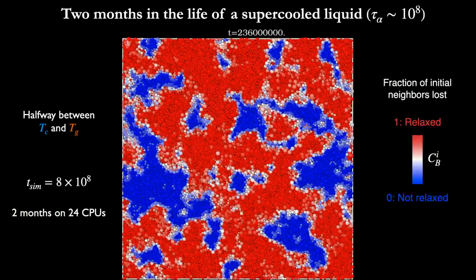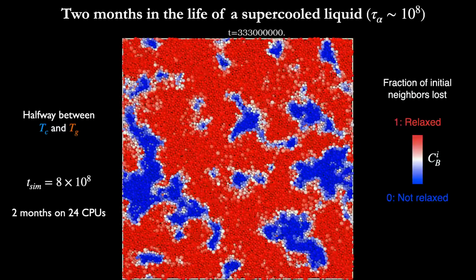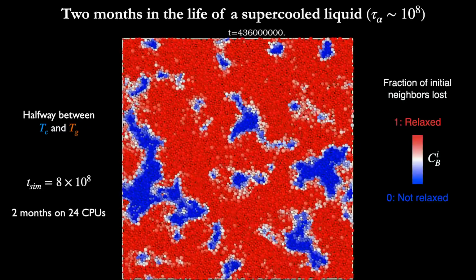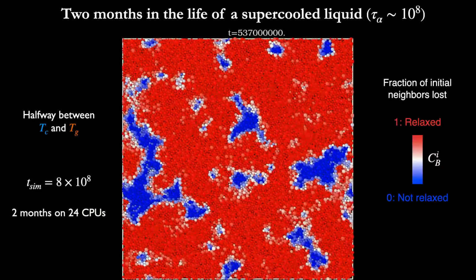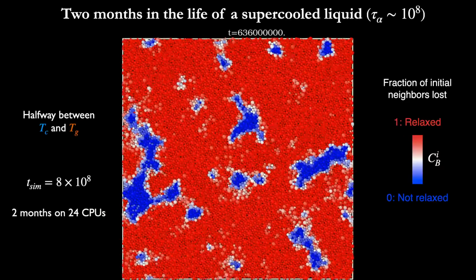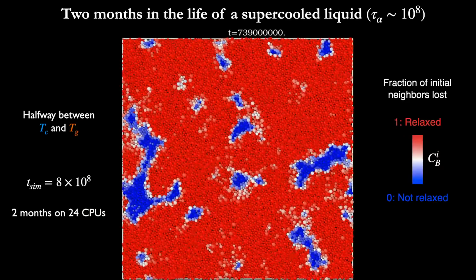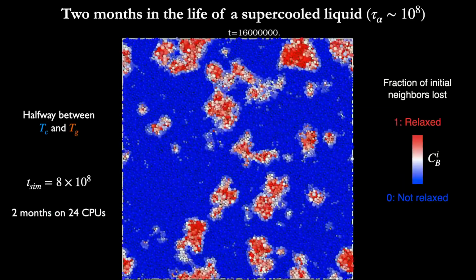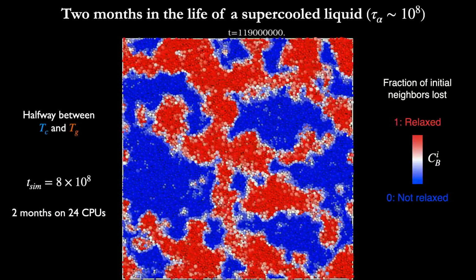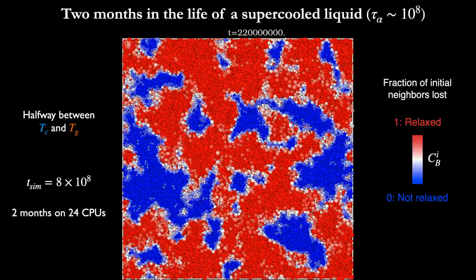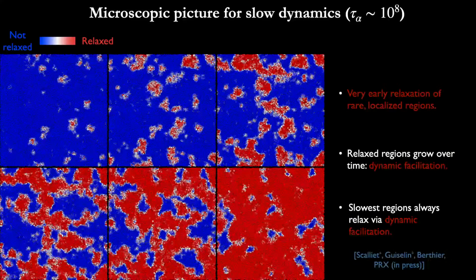you see some quite striking spatial temporal pattern here for the dynamics. Maybe you can actually see that even in these red regions, you still have a lot of rearrangements. And eventually, you have some regions that have not relaxed even after several relaxation times.